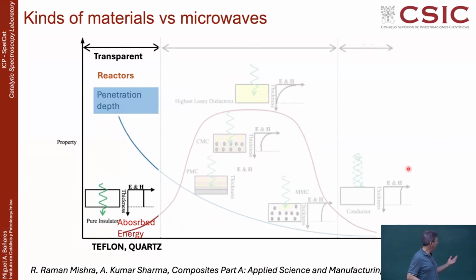And so when you design a reactor, you have 3 categories of materials. Some of them are transparent materials. Transparent material doesn't interact with microwave, which is good because the microwave goes through them. That is a material that has a very high penetration depth. So it allows the microwave to go through it without a significant decay of the power. And it will not heat. So the energy which is absorbed by that material is very little. Materials like that are Teflon and quartz.